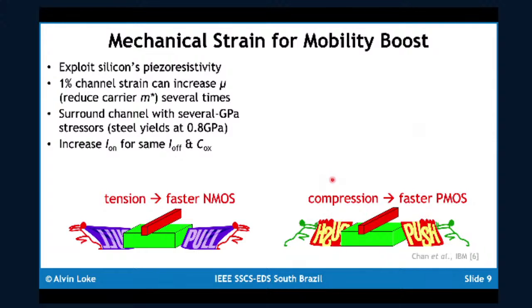We're exploiting the fact that silicon is piezoresistive, which means its electrical properties depend on its mechanical strain state. This is quite amazing, because if you can introduce 1% of channel strain, that can reduce the carrier effective mass of electrons and holes several times, such that you can actually increase the mobility several times.